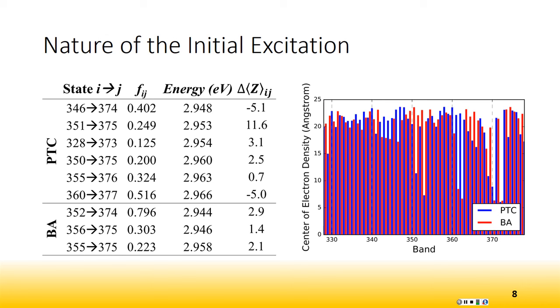So this is very important because we want to see charge transfer. From this diagram, we can make a conclusion that PTC facilitates charge transfer because it's either initially excited to a charge transfer state, or it has very few states to relax to get to a charge transfer state, whereas BA has to relax almost to the HOMO level.